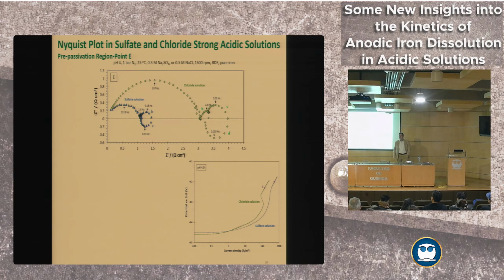And with this corrosion rate, isn't it expected to precipitate iron carbonate, because we have a very large concentration of iron? Well, apparently not here, and the other reason is that pH is acidic, so it is able to handle that. But if you went to pH 6, this would have gone all the way to passivity, or even with pH 4, if you went another few hundred millivolts up. So we caught it here just before passivity. This is the pre-passivation region. It's trying to, you see how it's not really increasing, but we caught it. We did not want to go that high. But yes, it could happen, you're correct.